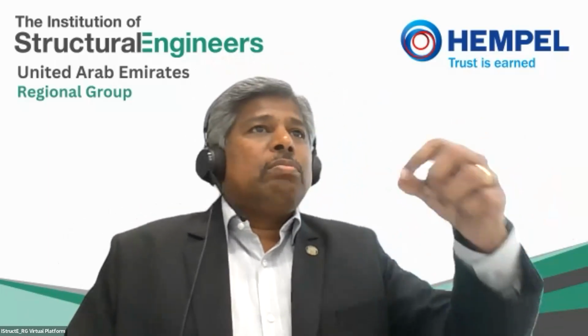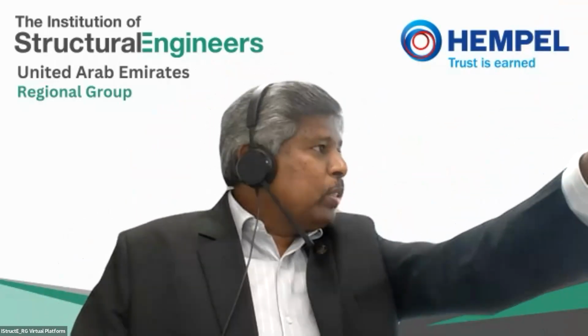But what is important is that if you have an existing structure, it is fairly easy, right? We can come and help you. If you have an existing structure, then what you do is take a pre-measured metal piece of standard carbon steel material. You can just leave it outside, and you can come and measure after 365 days to know exactly what it is.